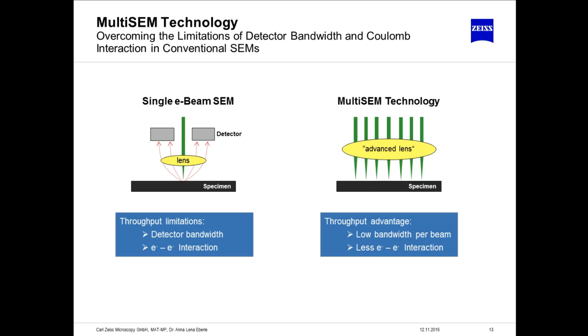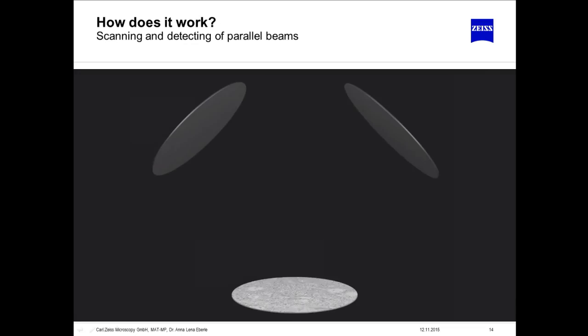One way to circumvent these limitations is going for multiple beams in parallel. This was the approach that Zeiss took while developing the MultiSEM. Now, we can spread the total current over multiple beams, and therefore we can keep a very good focus, a good resolution. And on the other hand, it's not necessary to scan beyond the standard level. The frequency can be kept at a normal range, and still we increase the throughput massively by using several beams in parallel. So, how does this work? This is, of course, the question. Let me start this little animation.